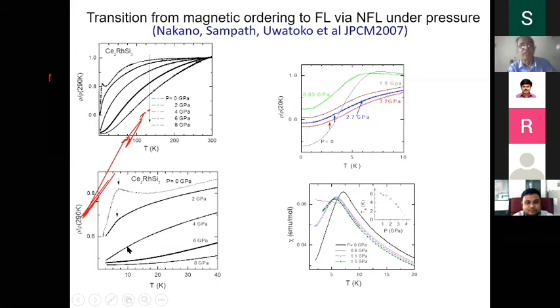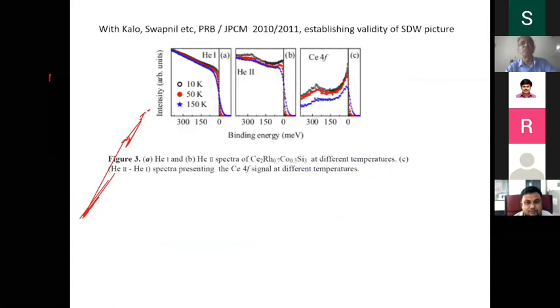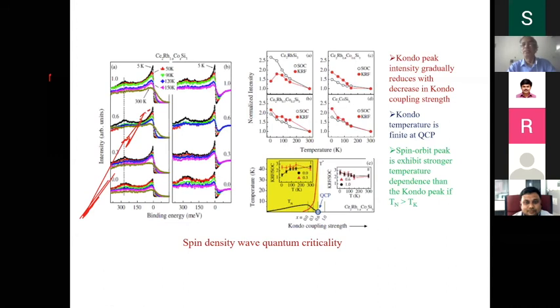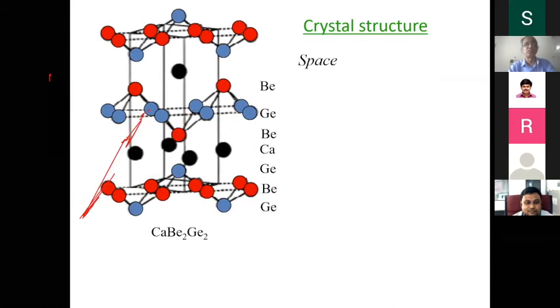This is a linear behavior. At high pressure, you could say quadratic behavior. Quadratic behavior, as I mentioned, is Fermi-liquid behavior, conventional metallic behavior. You don't see quadratic behavior here; instead it is linear behavior. So we are going from a magnetically ordered region to a non-Fermi liquid region to a Fermi liquid region. Even in the same material, you can go from a localized picture to a delocalized picture by varying pressure, and we have done spectroscopic measurements, which I will not go into detail, showing that even in the magnetic region you can see signatures of these features.